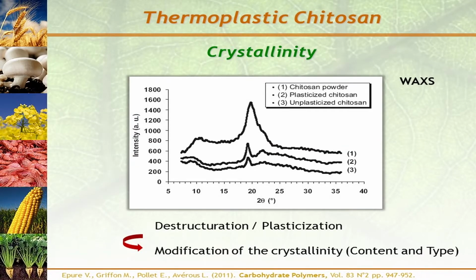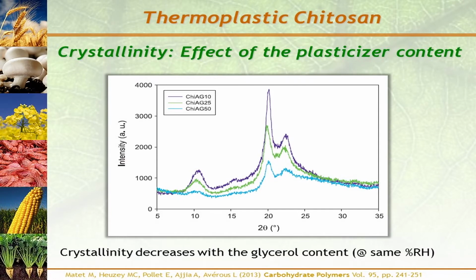So the crystallinity also varies a lot. Here you have the chitosan powder unprocessed, and after processing with or without plasticizer, you see a strong modification, a huge decrease in the crystallinity of the plasticized chitosan, and the crystallinity will be also influenced by the plasticizer content and the type of plasticizer. Here you have the glycerol used as plasticizer and increasing content 10, 25, and 50% compared to chitosan. And you see that the crystallinity decreases together with the glycerol content, and this for the same relative humidity storage atmosphere.